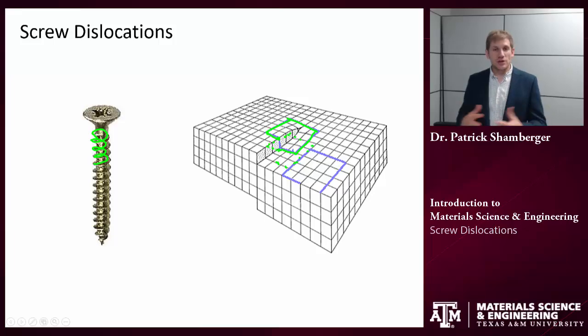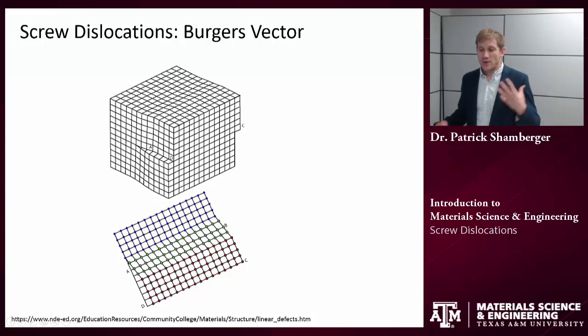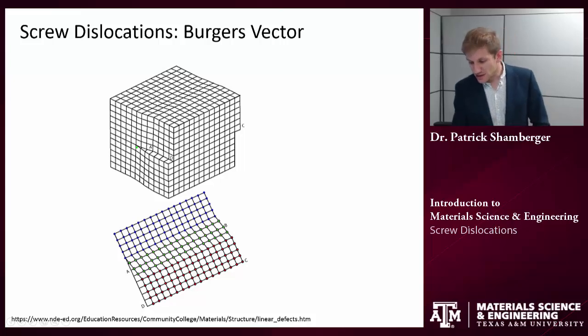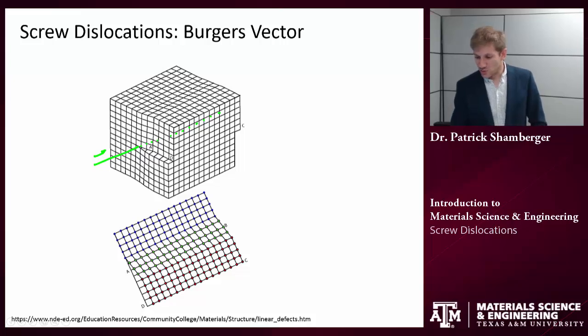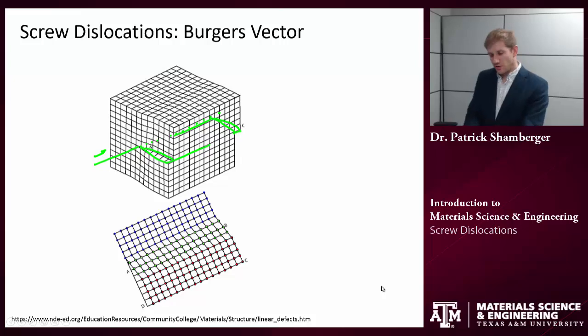Let's do similarly to what we did for the edge dislocations. Let's first start by describing the Burgers vector for the screw dislocation. A Burgers vector is a vector that completes a circuit that is drawn around that dislocation. The dislocation is a linear dislocation and it extends into the lattice this way. There's a plane of atoms that has been sheared so that the top half of this volume along that plane was sheared sort of back and to the right.